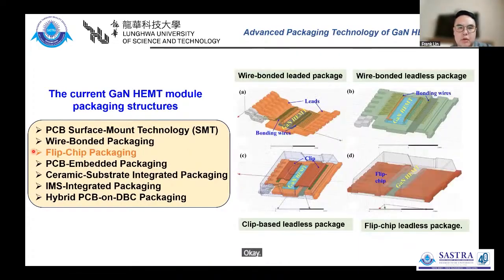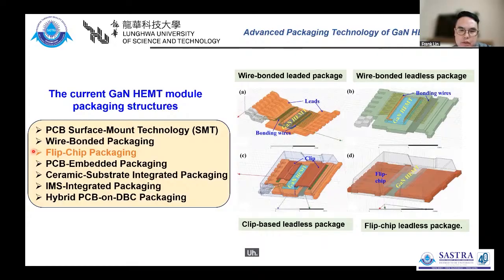Okay, let's introduce flip chip packaging. Unlike wire bonding, it uses short solder bonds, which greatly shorten the loop length, lower parasitic inductance, and enable high density integration. A study showed that flip chip packaging has 6 times lower inductance and 15 times lower resistance than wire-bonded ones, highlighting its clear advantage. However, its thermal performance is limited, making it more suitable for low power applications.